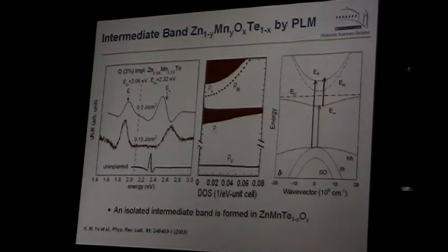So this was a theoretical prediction. But using our PLM, or pulse laser melting, method, we attempted to synthesize zinc oxide telluride. In this case, we took, in fact, zinc manganese telluride because we had a kind of premonition that manganese could stabilize oxygen.